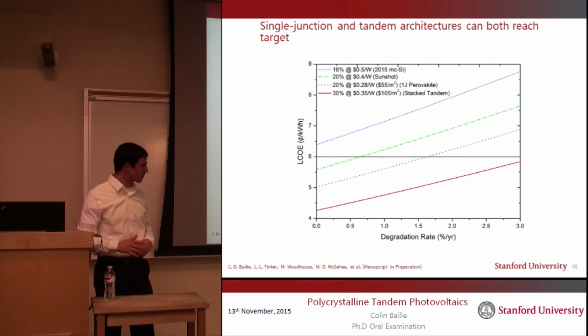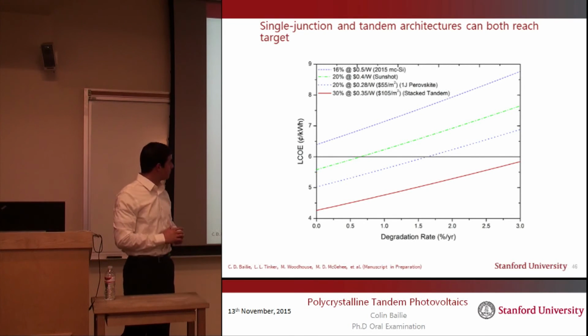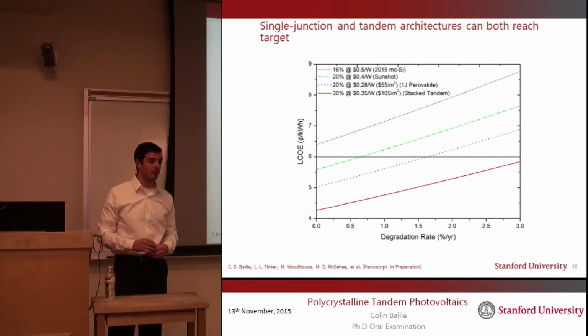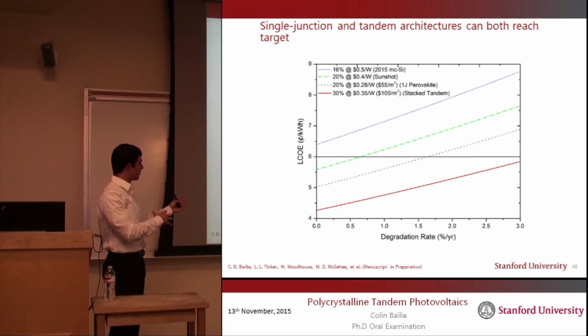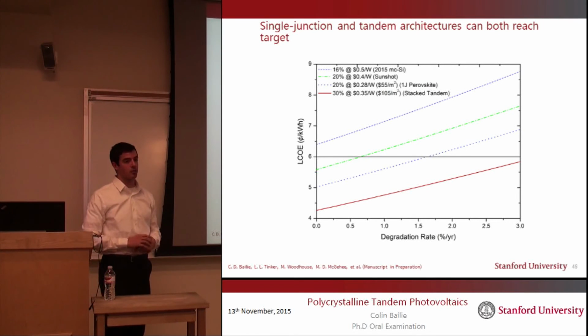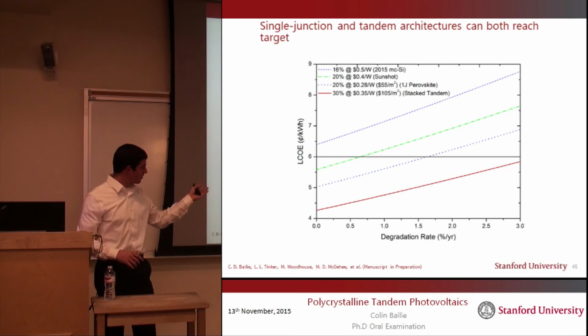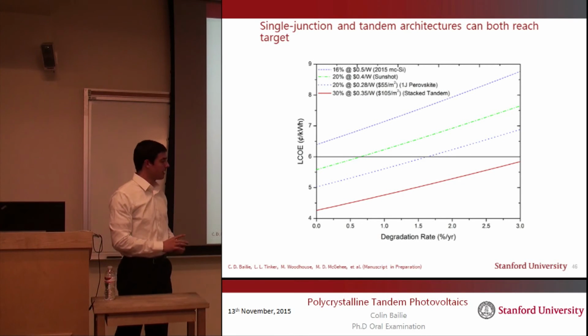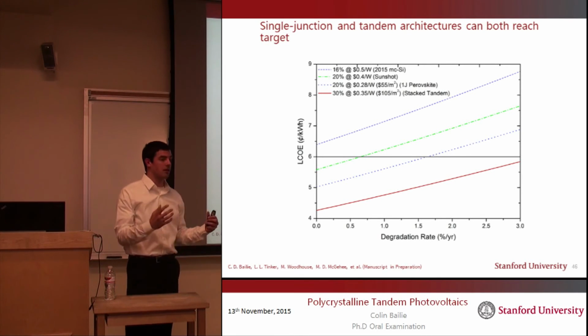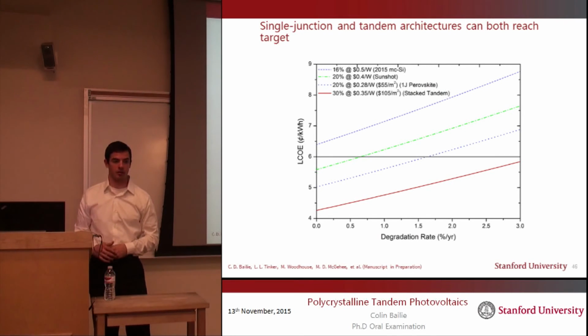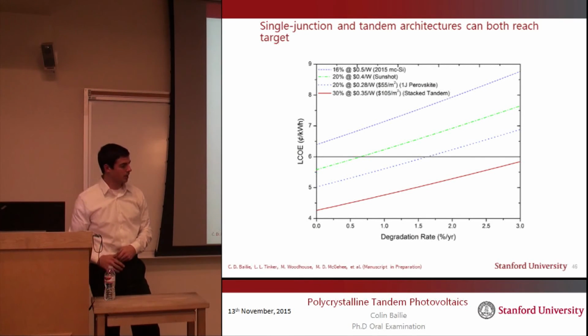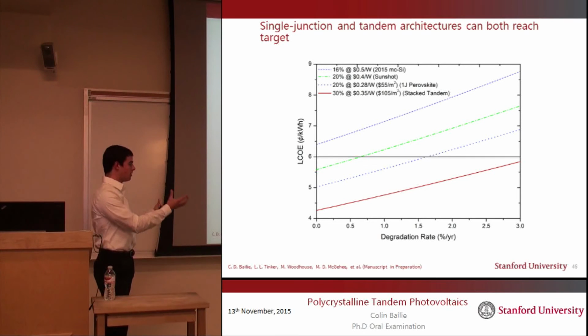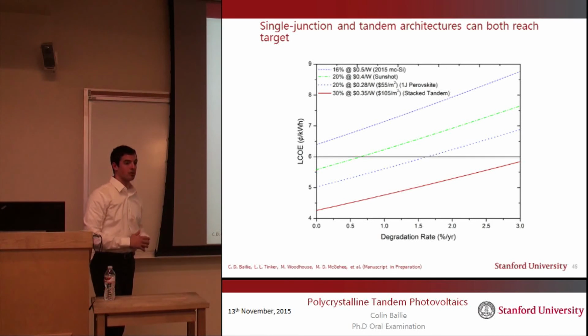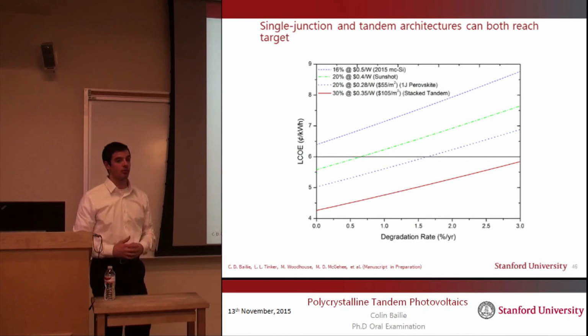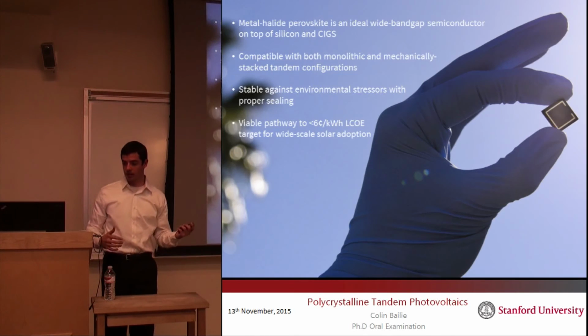one and the other. But the bottom curve is a mechanically stacked tandem, where now we're assuming it's 30% efficient and $105 per meter squared. And for much of the degradation space that we're looking at here, you can get below 5 cents per kilowatt hour for your system. And so this represents a major change in the price of solar and can make it competitive with these other technologies.